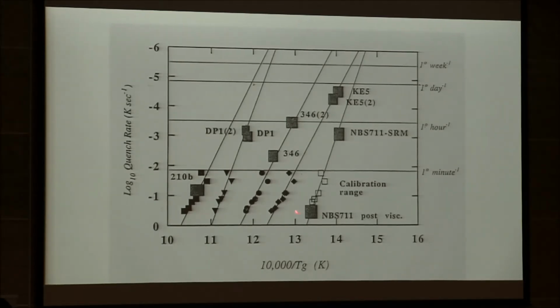These are real results. Every big box corresponds to an actual naturally cooled glass. Over on this side you can see they come down from degrees per second to degrees per day. And so if this is a characteristic of volcanic glass, you can go out into the field blindly, take glass samples, and have an idea of how this unit of glass formed in the field. That's a big part of modern volcanology.